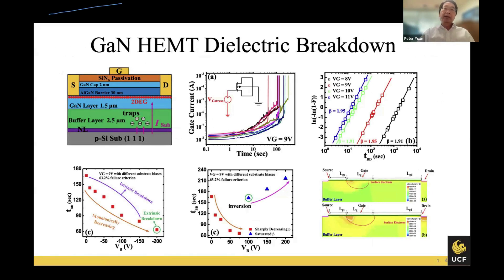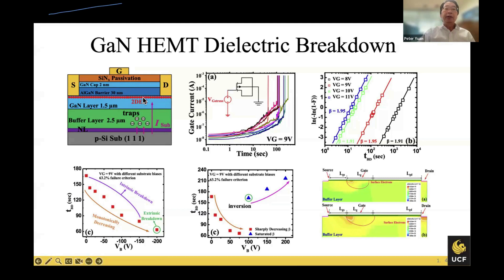The first reliability phenomenon for gallium nitride HEMTs is dielectric breakdown. Looking at this power transistor, there is a gate-source terminal. Under the gate, we have a passivation silicon nitride layer and aluminum gallium nitride / gallium nitride layers that form a two-dimensional electron gas — the basis of high-speed electronics for high-frequency applications. The issue presented here is gate leakage current subject to high-voltage gate stressing, showing leakage rate with some kind of random distribution. This is experimental measurement data from many HEMT devices showing statistical variations.